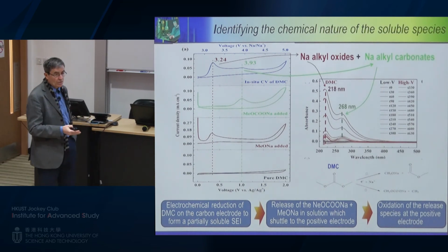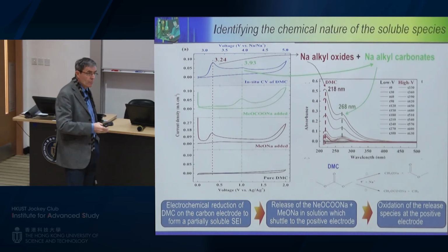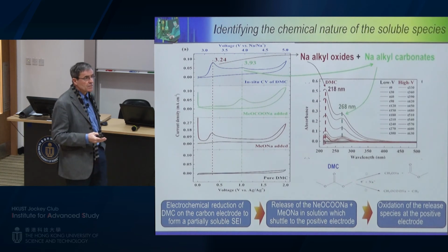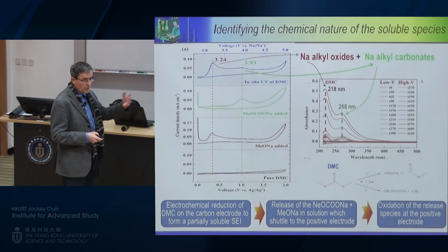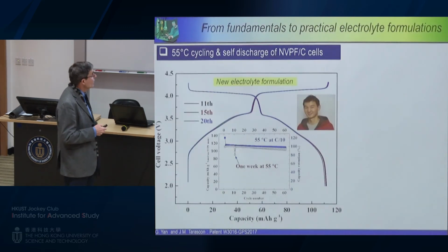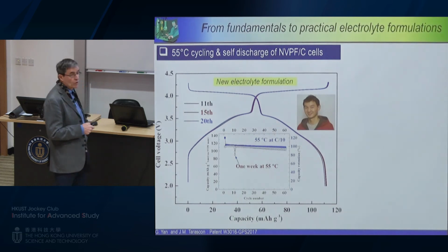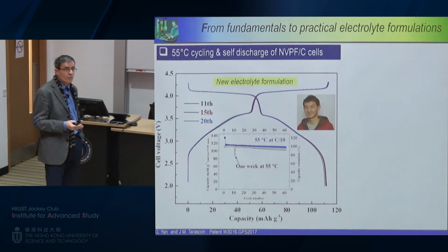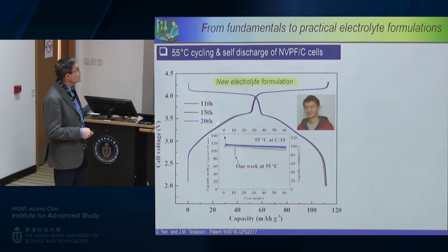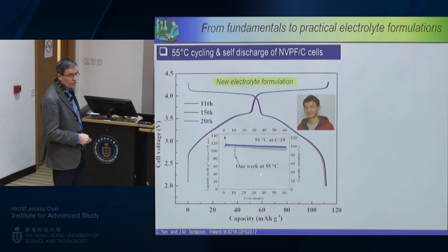Knowing this, of course, now we are able to go back and design the right electrolyte by putting different additives. And this is more or less the work that has been done. Of course, I will not tell you what this new electrolyte formulation is, but as you can see now, we can go to 55 degrees C. You can see here 20 cycles at 55 degrees C. You see perfect cycling, and you can see here after 1 week of storage and so on.